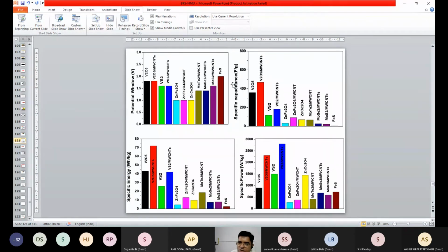This is the specific capacitance for the complete solid state device, and this is the champion cell. Vanadium oxide coated on the carbon nanotube shows a very high value of specific capacitance. For specific energy, vanadium oxide is the champion. For specific power, vanadium sulfide is the champion in terms of the solid state device.